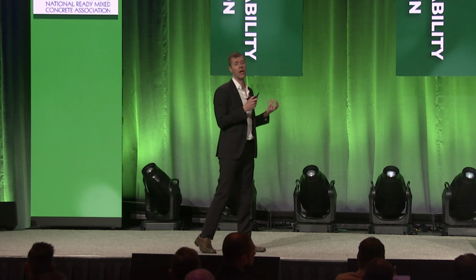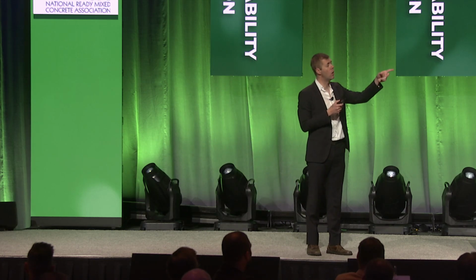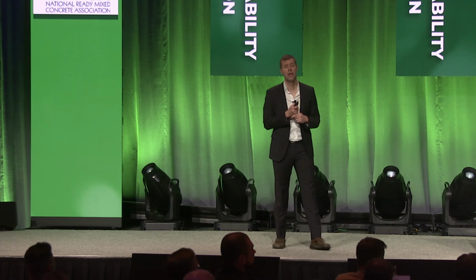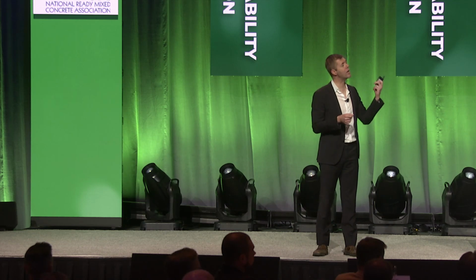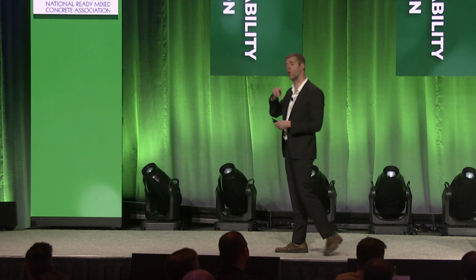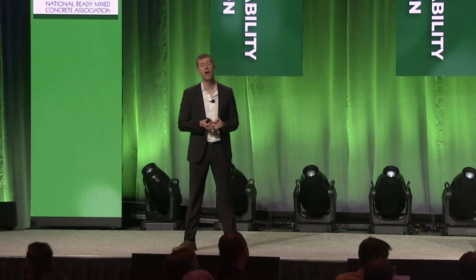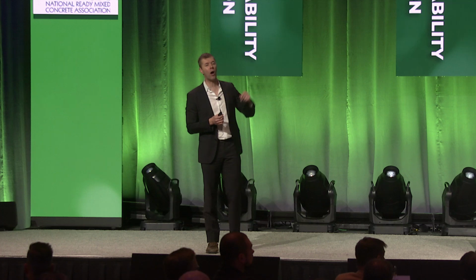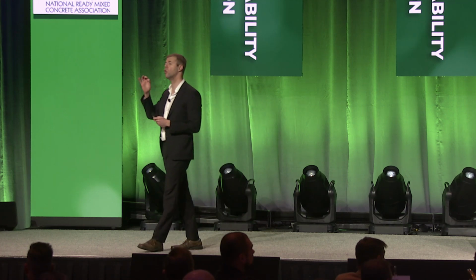Gradation matters. And a tool that's simple, a tool that's easy, a tool that was developed with $1.5 million of research, was this one, the tarantula curve. It was developed out of my lab. On the x-axis is the sieve number. On the y-axis is the percent retained. And it's a total aggregate distribution that goes inside those curves. And one thing that's cool is every time you go outside one of those limits, we have told you specifically what's going to go wrong, because we've done it in the lab and the field again and again and again. And this is an essential tool that I use to design all of these concrete mixtures.